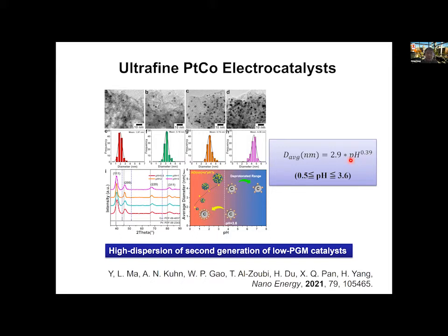So this is what we actually achieved based on the simple principle of tuning the pH around the point of zero charge. If you look at this cartoon illustration, we can start to tune the particle sizes of the platinum cobalt catalyst, primarily on the low pH side, and you'll find that the smallest particle we can get is roughly about 2 nanometers in diameter, and it increases to about 4 to 5 nanometers right around the point of zero charge range.